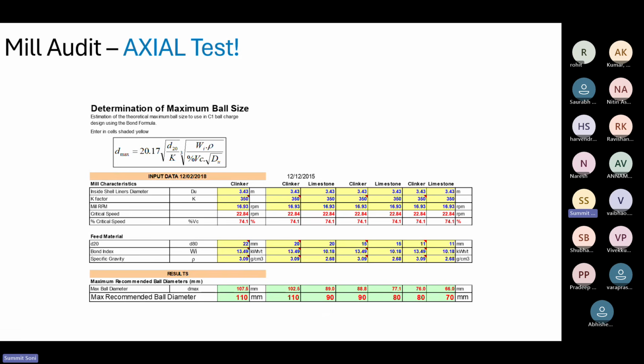Usually we take the mill inner diameter, the K factor is usually a constant, 350. We consider the RPM, and the critical speed is calculated based on the mill RPM. And we use that in this calculation. Along with that, we also take the granulometry of the raw material that is going into the mill. And we consider the Bond index based on the various raw materials. Let's say for limestone, we have taken 10.18. Clinker, we are taking 13.49, and so on and so forth. It's a simple Excel sheet, but it is very crucial when you're starting your ball charge design.